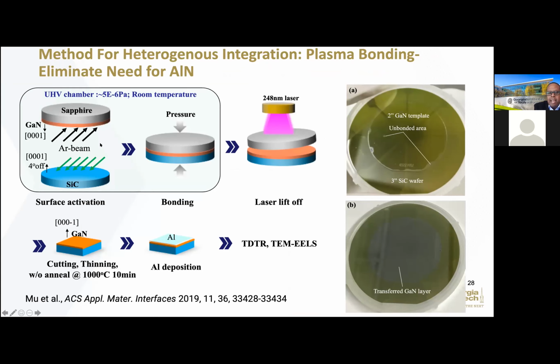And so here we have gallium nitride grown on sapphire. You can actually take this, use an argon ion beam to activate the surfaces, place them together under pressure, and then do a laser liftoff of the sapphire. And now you're left with this gallium nitride on this substrate. You can then do a smart cut to remove some of the gallium nitride to make it thin. And so we did this portion to make it thin in order to do thermal measurements of the thermal boundary resistance between the GaN and the underlying silicon carbide.